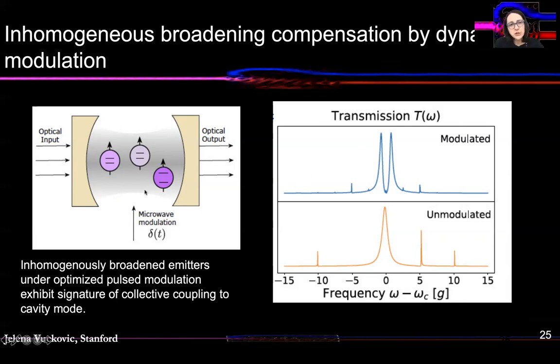However, we have recently shown that we can use a similar approach where we applied electrodes to a system of a few emitters, and we hope that it would also work for a large number of emitters, and then just apply an optimized microwave field. As a result, we can compensate inhomogeneous broadening in the system. In this case, we start from a system of three inhomogeneously broadened electron spins inside of a cavity. If you measure transmission through the system, you would not really see anything interesting. They're decoupled from the cavity. But if you drive them at the same time with the optimized microwave signal, you will see a rapid splitting of the cavity because they become collectively coupled to the cavity resonance.